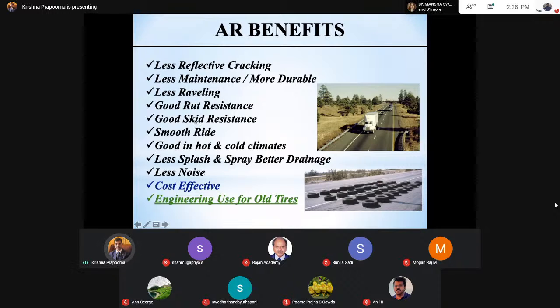Skid resistance, because it is open texture or gap texture. Definitely smooth ride, very good ride comfort. And I showed you a picture both in cold climates and hot. In fact, I was there in Arizona and Sweden. In 2010, in 1 year, I have felt, I've experienced 70 Celsius pavement temperature in Arizona, and I moved to Sweden in the same year where I saw minus 46 Celsius. So you can see a range of temperature, and we have seen asphalt rubber in both conditions working very, very fine. In fact, less splash and spray because of high porosity.